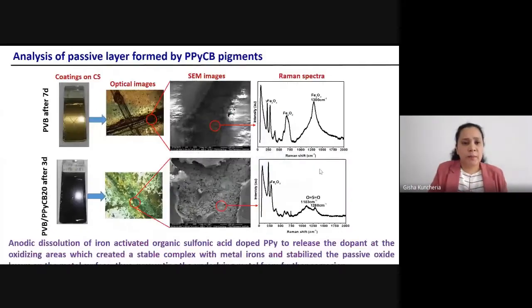Now we used some microscopic and spectroscopic techniques to find out this self-healing behavior. This is the pure PVB coating, and if you look clearly, you can see there is a cross cut. What is the purpose of this cross cut? We want to analyze these corrosion reactions within a short time. Otherwise, we have to wait a long time. That's why we purposefully made some defects on the coating using a surgical blade.